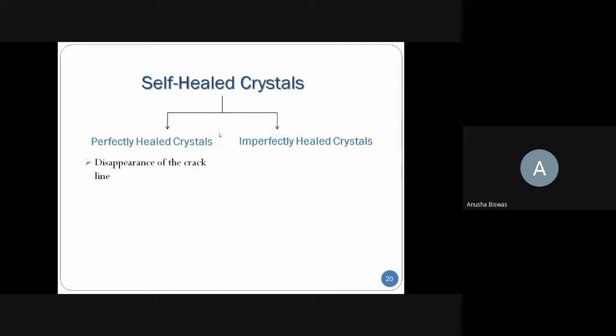Therefore, in a perfectly healed crystal, the crack lines almost disappear in scanning electron microscopy and other microscopic techniques also, and the alignment of these two broken fragments is done properly so that the crack disappears and the healed crystal behaves like a single crystallographic unit.